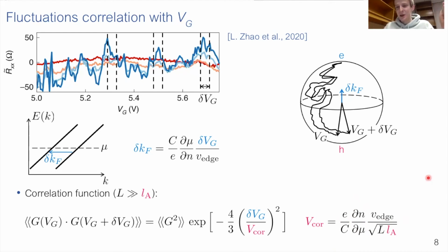First, we see that quite reasonably, the correlation radius in the signal becomes smaller if we make the proximitized segment larger. And this is reasonable. Essentially, the two spins have more time to diverge from each other. But what's a bit peculiar about this expression is that it has the Andreev length in the denominator.